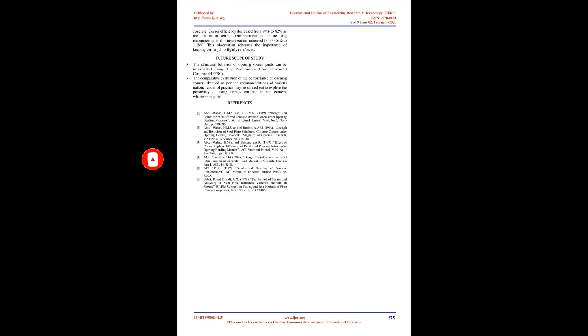An efficiency factor marginally in excess of 90% was obtained in the corner specimen detailed with a reinforcement arrangement which was conceived as a modification of detailing commonly used at construction sites. In this detailing, the main tension reinforcement of the framing members was extended to the far end of the corner and then bent in the corner joint as a 90-degree hooked extension.